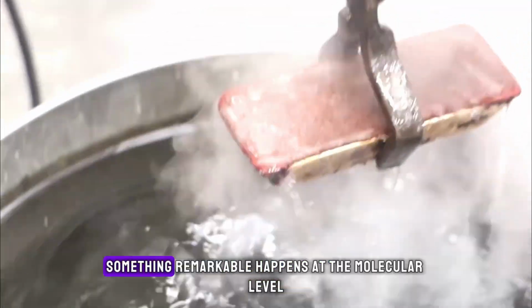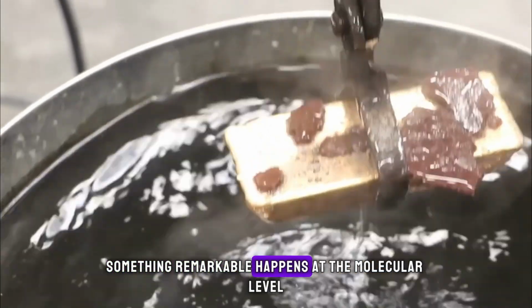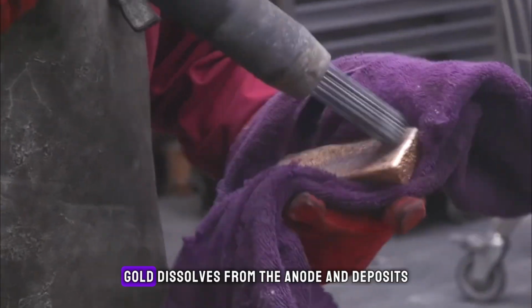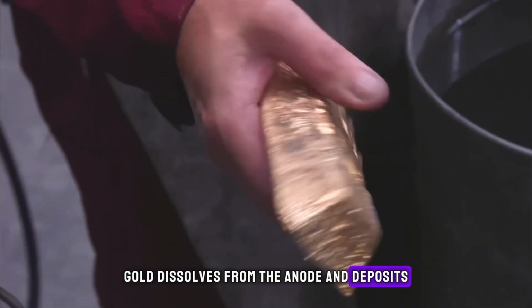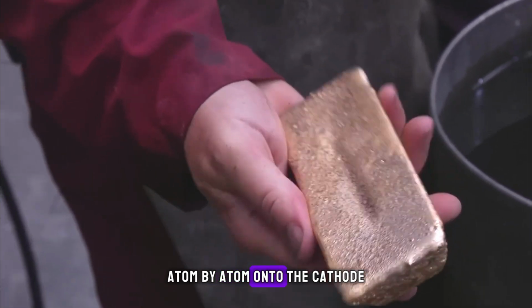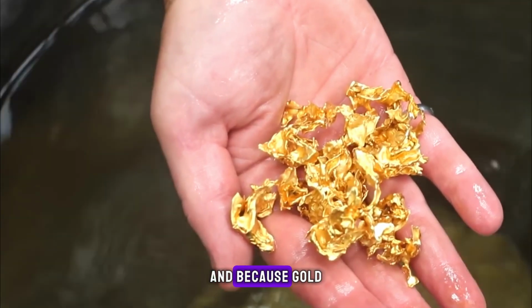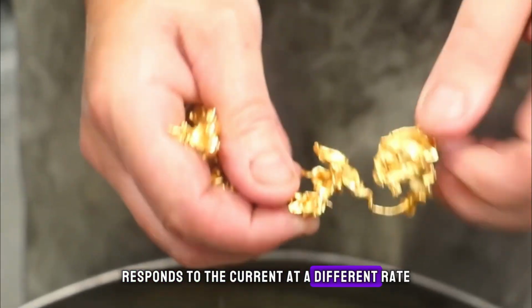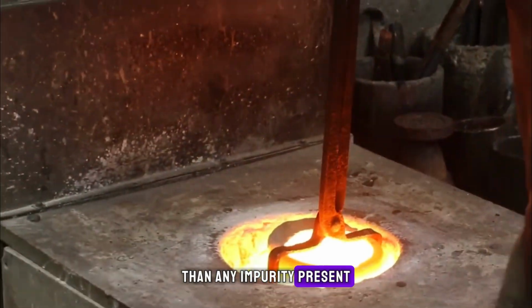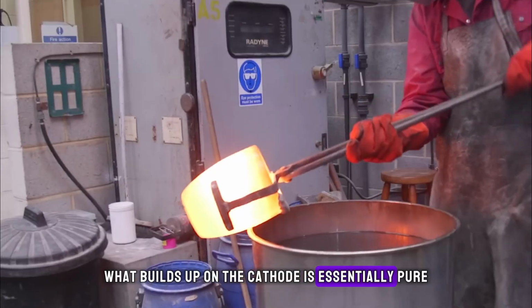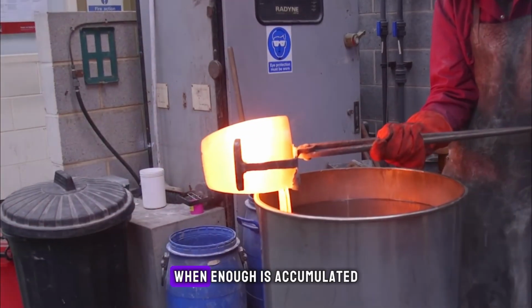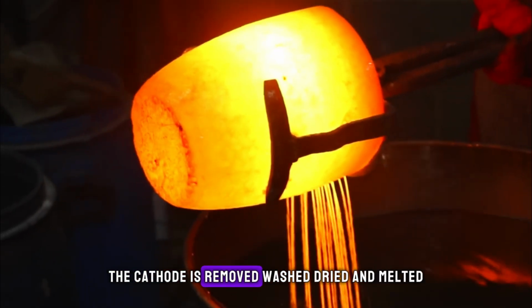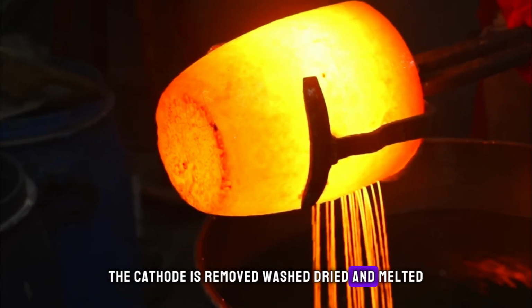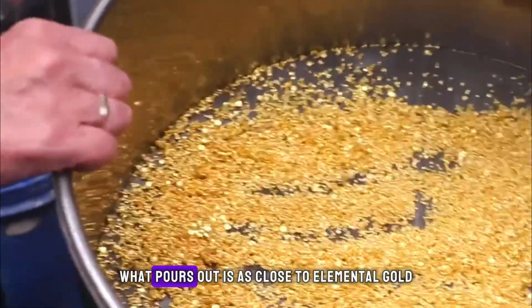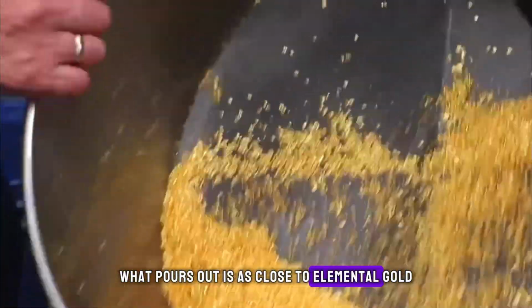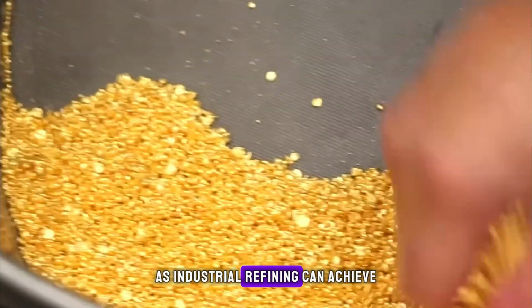At that point, something remarkable happens at the molecular level. Gold dissolves from the anode and deposits, atom by atom, onto the cathode. And because gold responds to the current at a different rate than any impurity present, what builds up on the cathode is essentially pure. When enough has accumulated, the cathode is removed, washed, dried, and melted. What pours out is as close to elemental gold as industrial refining can achieve.